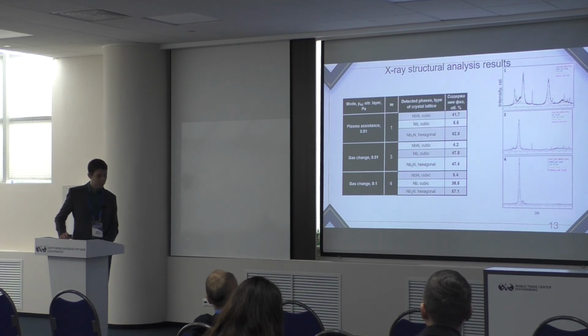It was revealed by X-ray diffraction analysis what phases the coating consists of. In multilayer coatings obtained by changing gases, the content of niobium is revealed, and in coatings with plasma assistance we have a lower content of niobium, and the nitride phase is revealed.